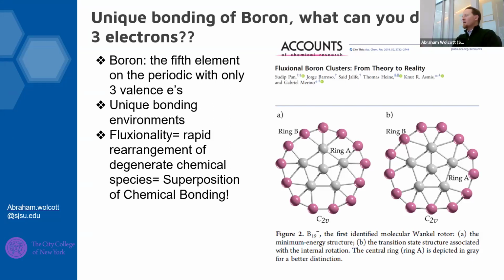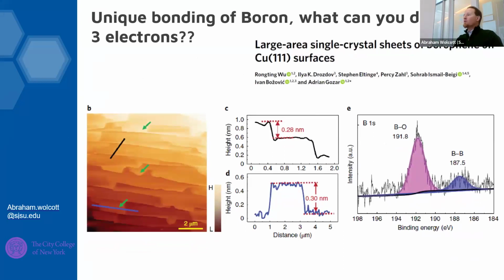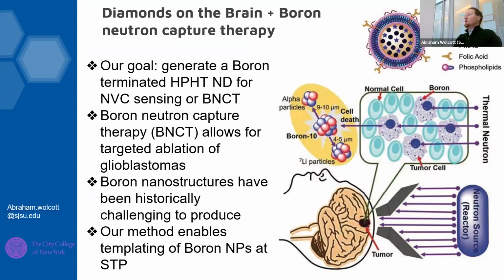And I would recommend you look at the paper that you can see over there on the right-hand side. Why do we care about boron? Well, it's an analog to carbon. People have made borophene. It has unique electronic structures, which can then be used in optoelectronics and electronic devices. This was only recently realized, to get single and bilayers of borophene, and much of the DFT was confirmed experimentally. On the right-hand side, you can see a little bit of XPS, where boron-oxygen bonds and boron-boron bonds have been confirmed, and I'll use a little bit of XPS in the near future to confirm our boron chemistry on diamond.